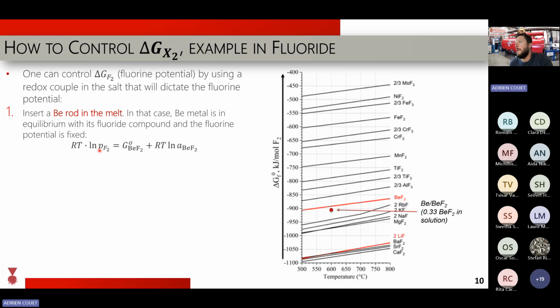And if you look at FLIBE salt, then the partial pressure of fluorine will be about here, and aluminum, titanium, manganese, all of these are going to be stable in the salts. So those are the best salts, right? But it's kind of difficult to do that in a real reactor because you need to put beryllium metal a little everywhere, and that's not the best, of course, both for toxicity and for salt thermophysical properties.